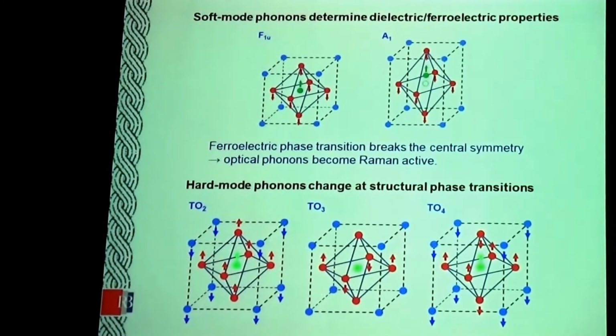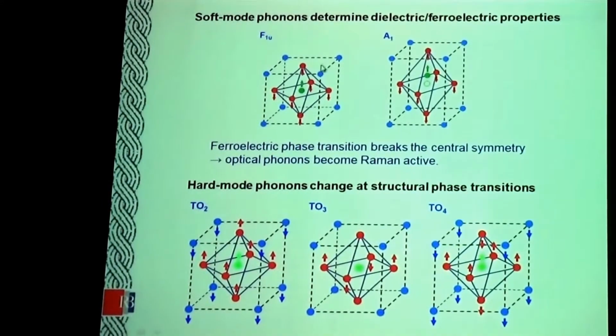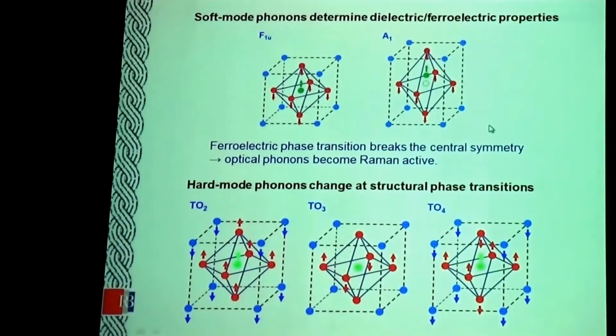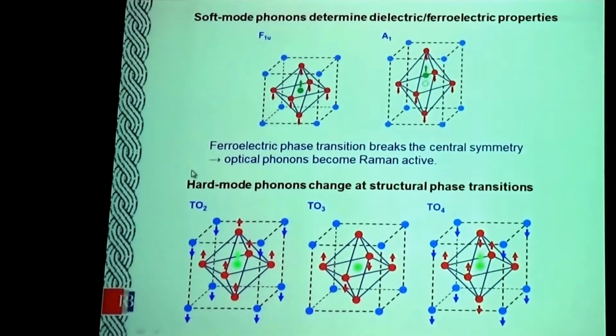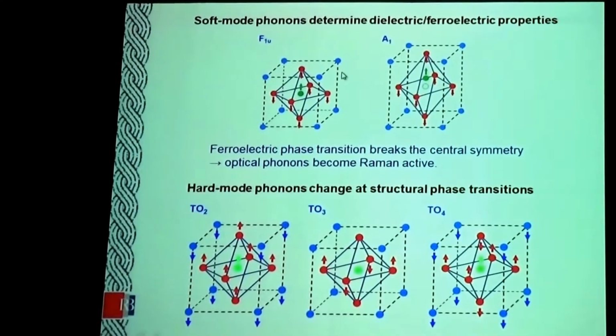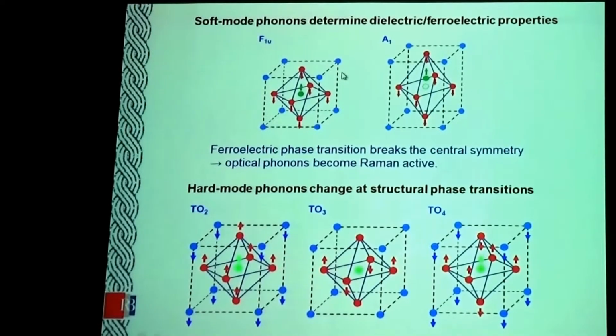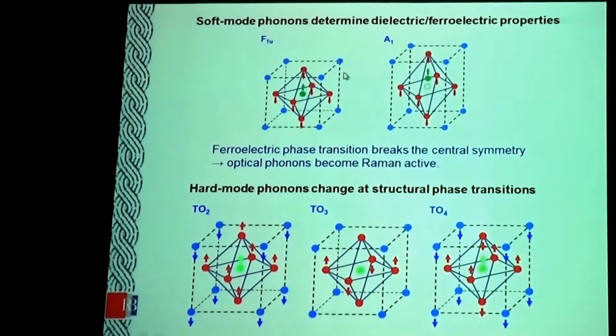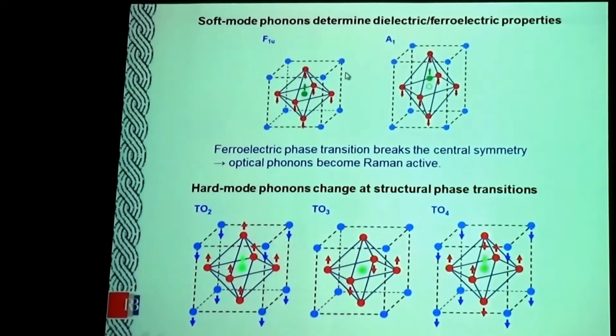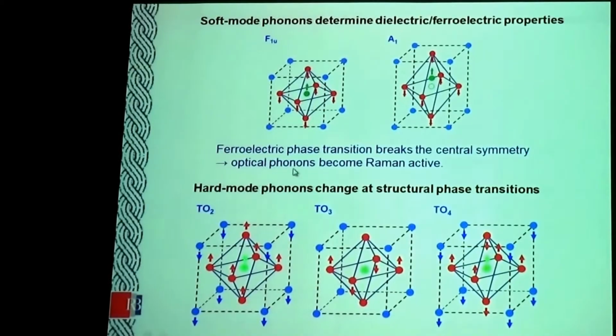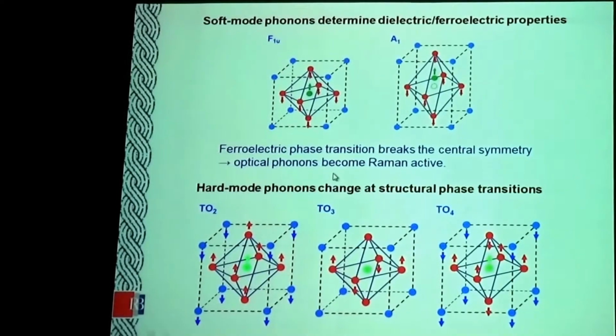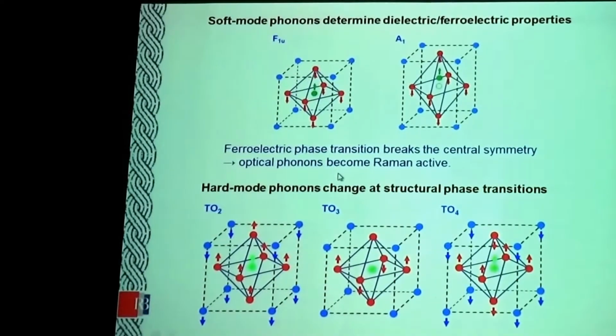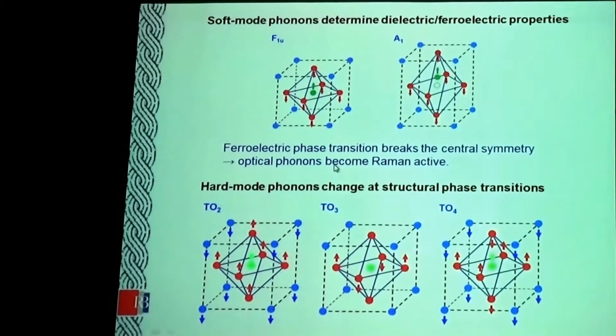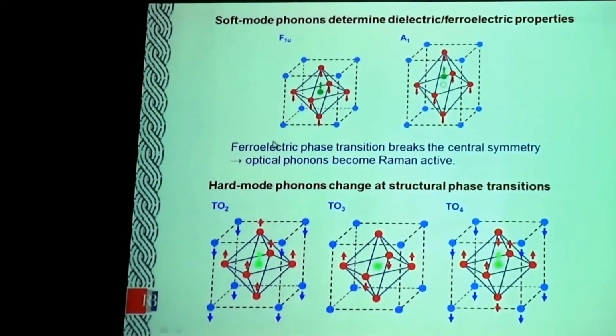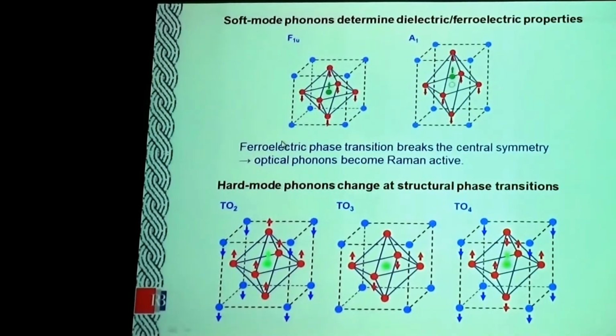As I already said in the beginning, I will say a few words about soft modes in ferroelectrics. When we have a ferroelectric transition, we have the break of central symmetry, so we don't have a cubic structure. Usually a cubic structure has either one Raman band or no vibration at all. After the ferroelectric transition, optical phonons become Raman active, and you can also see the phase transition from ferroelectric to paraelectric state. Hard mode phonons appear or disappear during the structural phase transition.